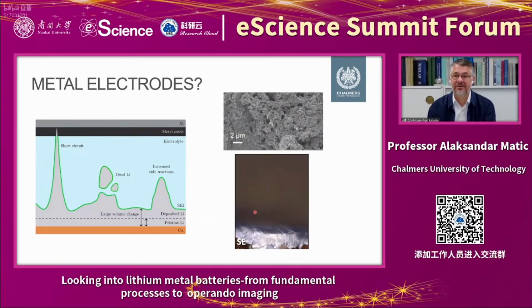And here is just to demonstrate how things look. Up here is an SEM image of how it can typically look after deposition of lithium metal on a substrate. So you see it's not a very dense bulk phase. Instead, it's very porous. It looks like a mossy structure.